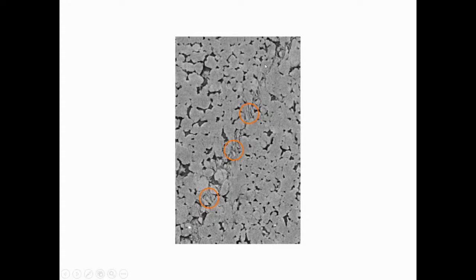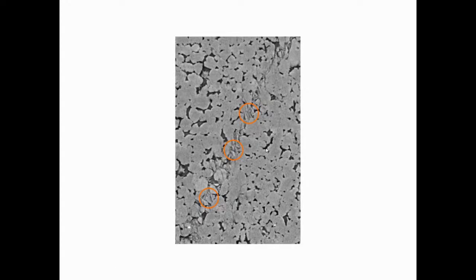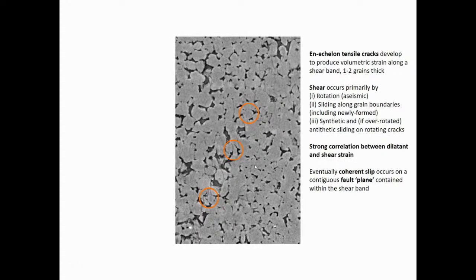And then you can also see that there's no fault. It's just a shear zone of deformation. And there's a mixture of tensile and shear deformation associated with microcracks and sliding along grain boundaries. And rotation is really one of the big processes accommodating the movement of the hanging wall over this footwall here. So I think I've said all of this. But eventually, coherent slip occurs in a contiguous fault plane. Eventually, you do get a breakthrough, and there really are two bits which are not in contact.